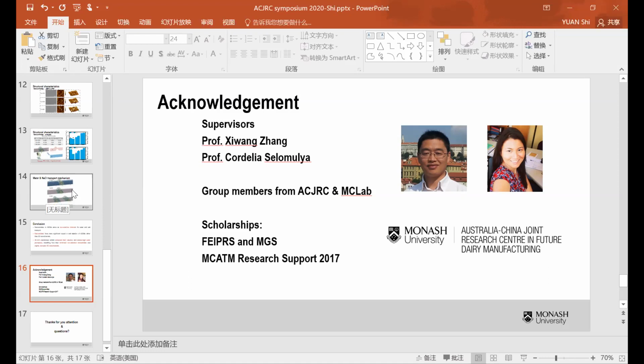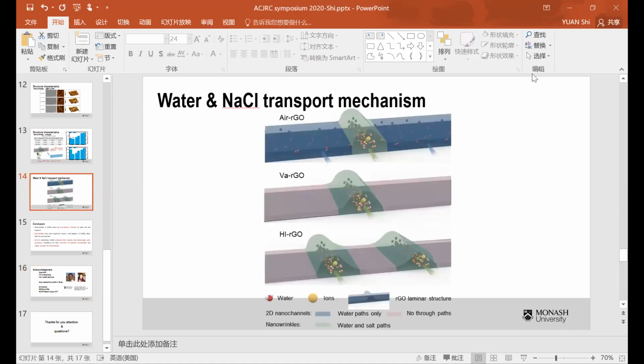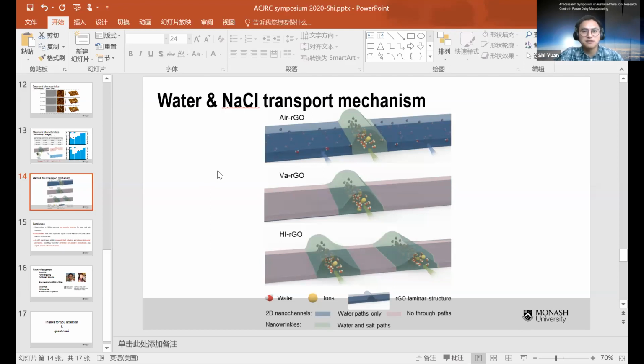I mean, if the nanowrinkles can be tuned in order to achieve the targeted performance, some other nanochannels like the defects you mentioned may also be beneficial if we can achieve controllable modification approaches, like through the geometric design or something. Yeah, might be, but my target here is the rejection of small cations. So when it goes to sub-nanometer, it's very difficult to tune the defects or the size of the defects. So it's quite challenging, but it's a way to further increase the performance as well.